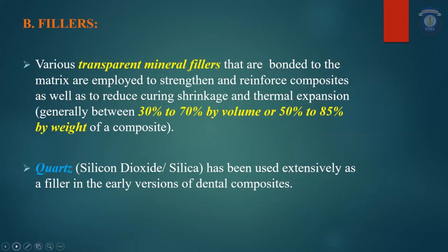There are many functions: they enhance the mechanical properties, reduce the polymerization shrinkage and water absorption, and also make the coefficient of thermal expansion compatible between the restoration and the tooth structure so that the interfacial stresses are reduced. Okay. And generally the filler loading will be described either in weight percentage or volume percentage. Either it is 30 to 70% by volume or 50 to 85% by weight.